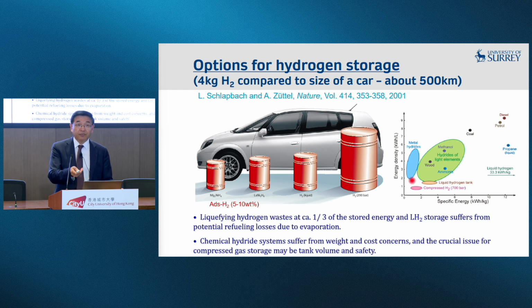This Ragone plot gives you an idea. So that's the metal hydride system. This is the specific energy. This is the energy density in terms of volumetric. And of course, diesel and petrol are here, very energy dense. Fossil fuels. And of course, this is methanol, the hydrides of light elements. Ammonia is here. And by the way, there's a lot of research going on about ammonia as a storage medium for hydrogen. But if you do the whole life cycle analysis, the energy loss is actually tremendous, right? So there are always pros and cons.